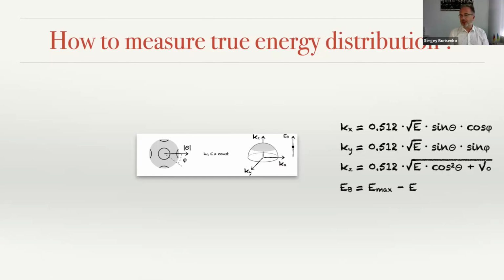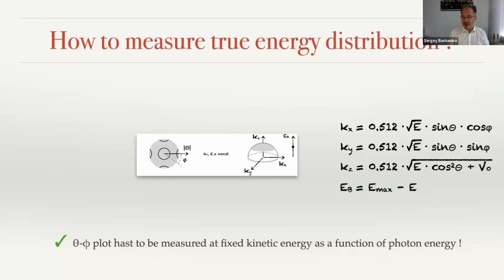Again, very simple. One looks at our straightforward equations and sees that if one keeps kinetic energy constant, one keeps momentum constant. So one needs to change this, and this can be changed by photon energy. It's a new method. I didn't try it myself, but we will certainly try. One keeps kinetic energy constant and measures theta-phi plots as a function of h nu. And then one gets the true energy distribution for every k point, a very transparent result. So it has to be measured as a function of photon energy at a fixed kinetic energy; for the 3-dimensional Fermi surface, you fix E at the Fermi energy maximum, and then you arrive at the 3-dimensional Fermi surface. So all natural, all within the method, native to the method.